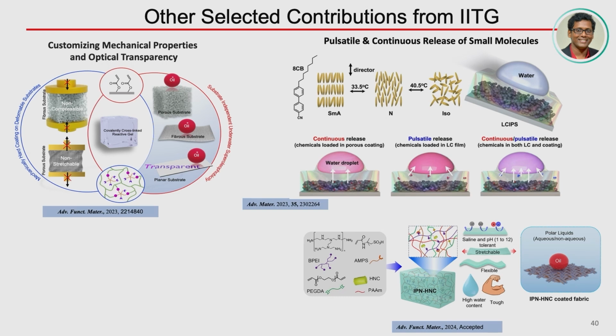Another one where we have introduced these highly hydrated coatings to separate liquids irrespective of difference in surface tension. People often talk about the separation of oil and water, but they are quite different in terms of their surface tension. One probably 72, another is 22 or 30. What about a liquid mixture where the surface tension difference is only about 2.5? Can you differentiate it? For that, you need a very tolerant underwater super oleophobicity. That is only possible when you have a very highly hydrated environment. That can also be achieved, and this was recently accepted in Advanced Functional Materials.